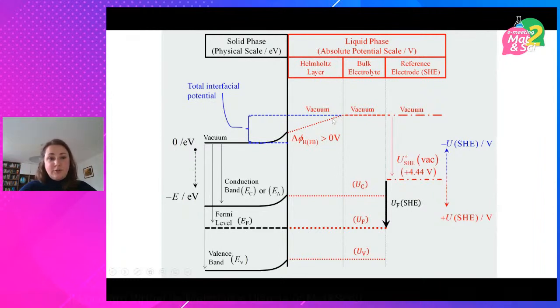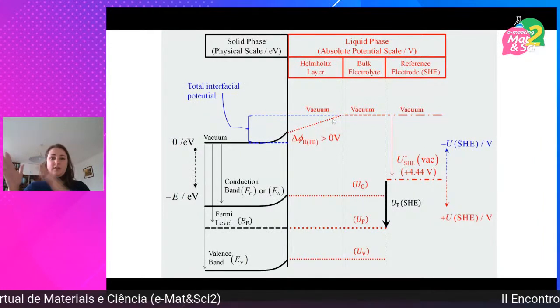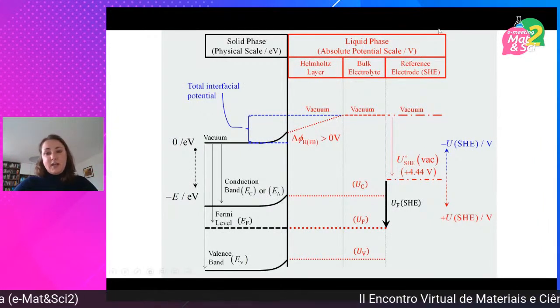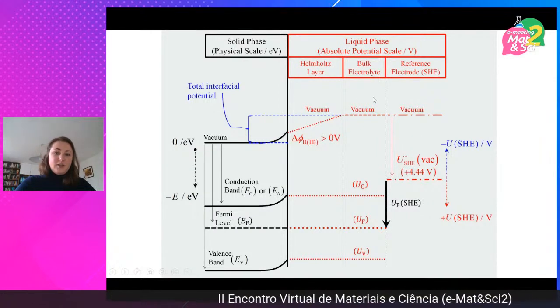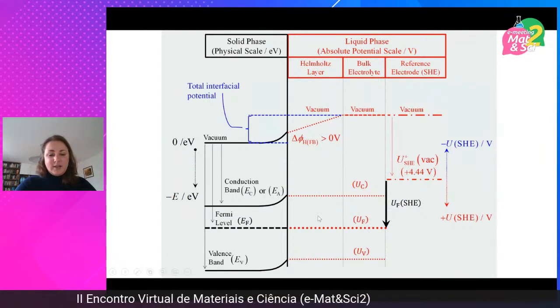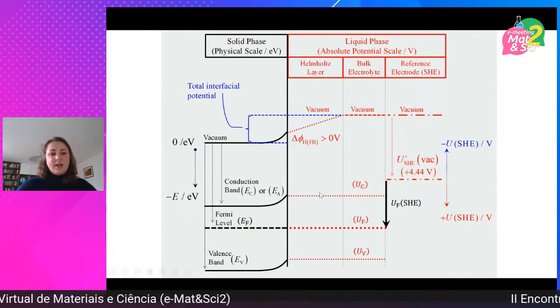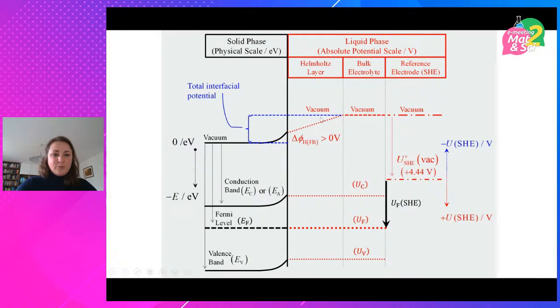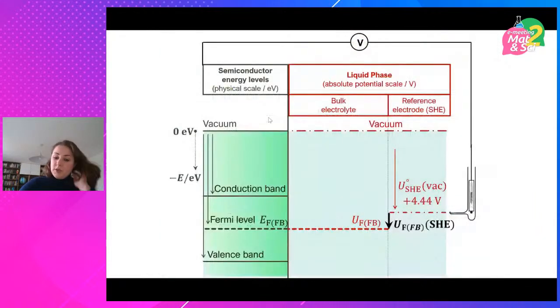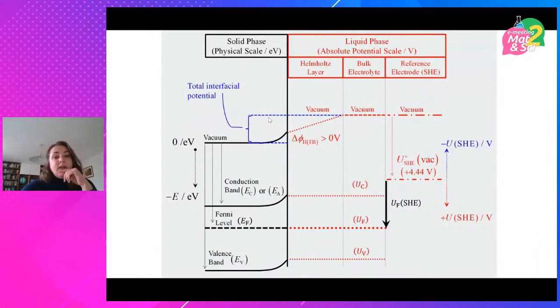So in this depiction, I've positioned the solid phase, which is a semiconductor, right in contact with the liquid phase. I've indicated where the reference electrode is, the bulk electrolyte, and the Helmholtz layer. It's not a particularly pleasant diagram, but I hope that the bits I've highlighted in blue, which say total interfacial potential, show that there is another contribution to the interface. And this potential drop across the Helmholtz layer very much depends on what pH you're at and how that solution pH differs from the pH of zero charge for a particular semiconductor.